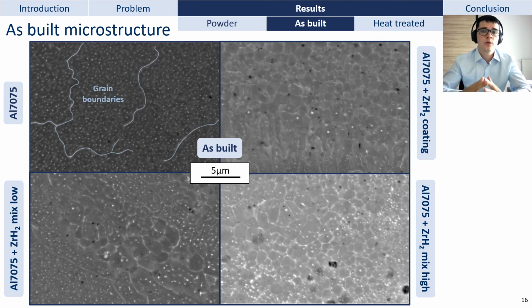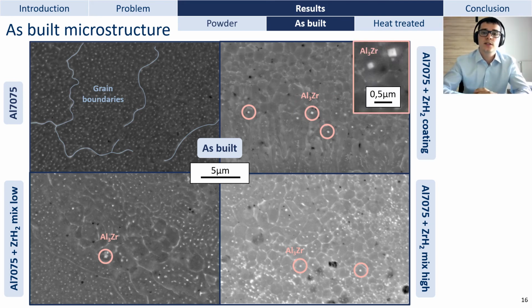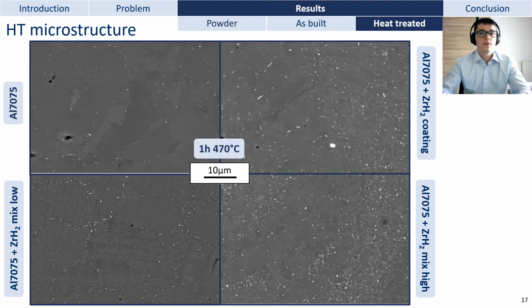Now, if we zoom in more, we can observe a few other things. First of all, we can see more clearly the precipitate networks that delimit the grain boundaries for the aluminum 7075, and the globular precipitates inside them. And the second feature to observe is the Al3Zr precipitates that are preferentially located inside the grains and that have a recognizable cuboid shape. And you can see a zoomed view of two of them just there.